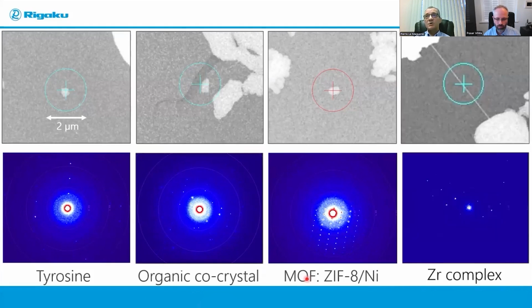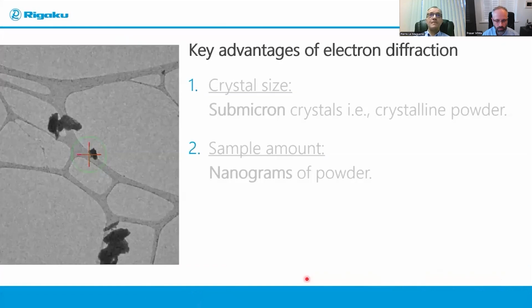And I've got a fourth example here. I don't have a picture of the powder sample for that compound, which was a zirconium coordination complex. But I still put that example on that slide because you see at the top right, that tiny needle is just beautiful. The thickness of that needle is maybe 40, 50 nanometers only. And you see still the nice diffraction pattern that we got from it.